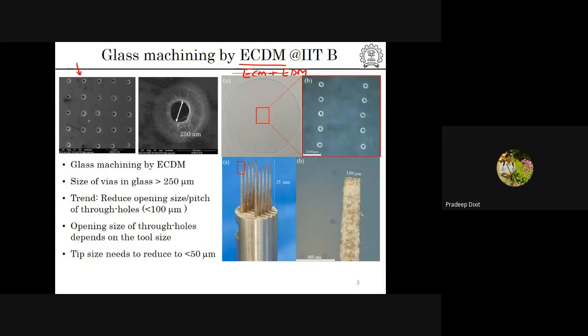For example, if you look at this picture here, this is a 5x5 array tool. The dimension is roughly about 250 micrometer. And what is the thickness of this glass workpiece? This is roughly about 500 micrometer. And on the right hand side, this is the same thing, but made by a 2x5 array tool. This is one hole here, and the array is shown here. On the bottom side, you will see the tool electrode which has been used to fabricate these through holes. This tool is made out of stainless steel, and the tip height is 15 millimeter. In the closer view of this tool tip, it is about 150 micrometers, so the hole is roughly going to be 0.25 millimeter.